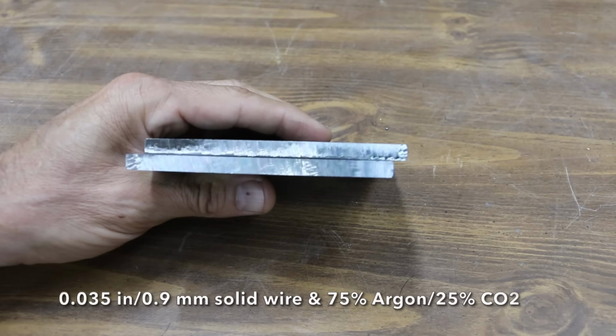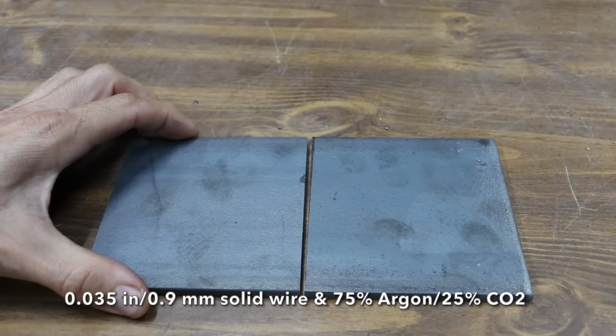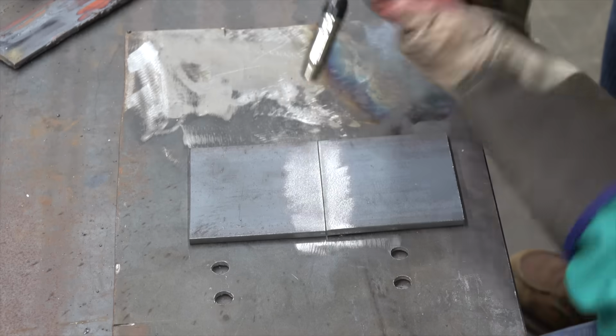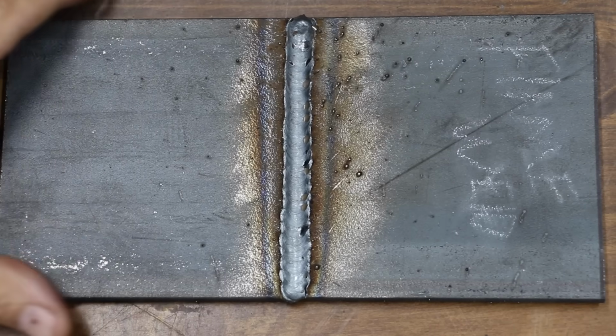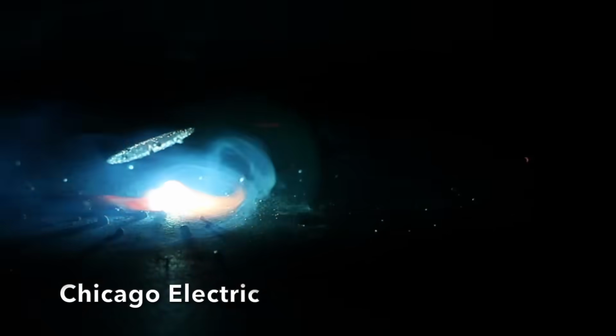In the next test, Virgil will be using 0.035 solid wire with argon CO2 shielding gas to butt weld quarter inch steel plate using the Flameweld. All the welding machines have been set up to get the best possible penetration. However, the Flameweld just doesn't produce enough current to achieve good penetration, but it does make a pretty nice looking weld.